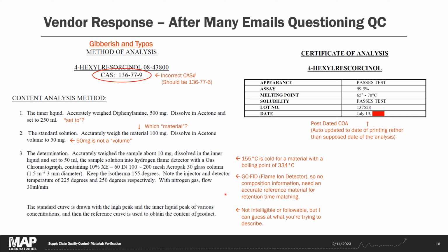One thing that's done sometimes to determine percent purity by GC-FID is to just integrate all of the peaks in the chromatogram, assume that the biggest one is your analyte, and calculate the percentage of the response that's coming from that analyte. So if that biggest peak was 98% of everything that you observed, then you would say 98% pure. But there's a big assumption there, and that's that the most common thing in the sample is the actual compound that it's supposed to be.